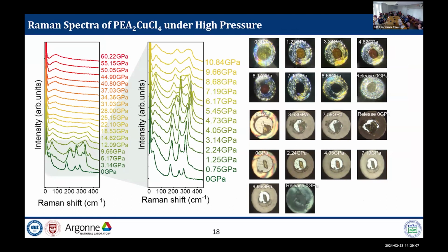This is a result of the suppression of the Jahn-Teller distortion; the octahedral symmetry changes from D4h to Oh at this time. So the d-d transition is disappearing and the charge transfer is more dominant. So the band gap is narrowing and the color changed. You can see yellow to almost orange to red to black. And the same thing happens in hydrostatic and non-hydrostatic conditions.